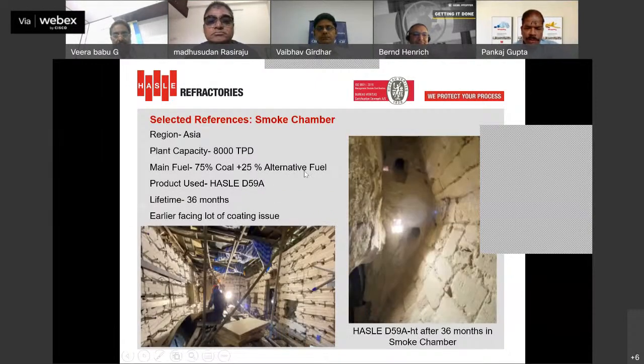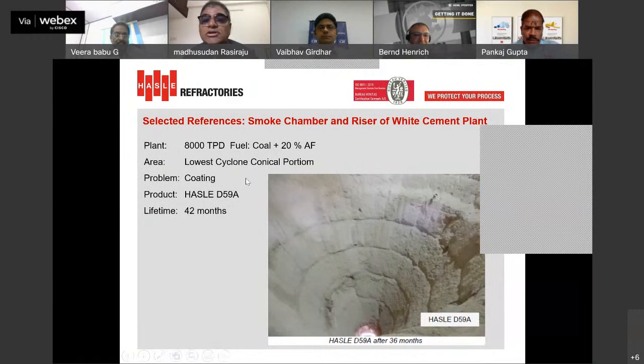So coming to the castable part, this plant is using 25% alternative fuel, and they used D59A castable, and you can see the condition after 3 years actually. So after that, they replaced the whole. Many plants are also facing problems in their lowest cyclone conical portion. So this plant is using 20% alternative fuel, and they are facing a lot of coating issue in this conical part of the cyclone. And we installed their D59A castable, and they were able to achieve 42 months with less and less coating problem in this area.